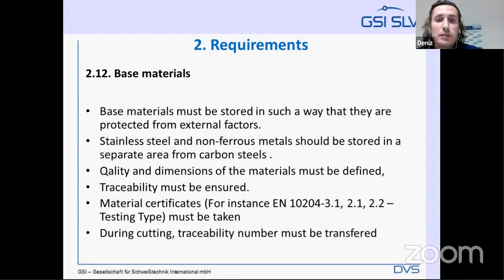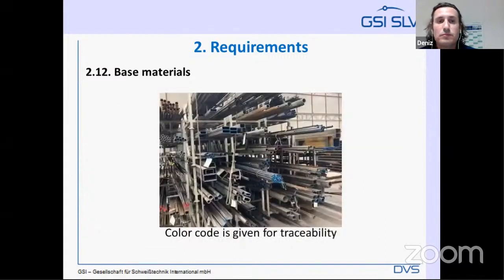Base materials. Base materials must be stored in such a way that they are protected from external factors, for example, humidity, dirt, rust, etc. Stainless steels and non-ferrous metals should be stored in a separate area from carbon steels to prevent corrosion risk. Quality and dimensions of materials must be defined. Traceability must be ensured. Material certificates, for instance, EN 10204 3.1 or 3.2, 2.2, must be taken during the cutting process. The traceability number must also be transferred for base material. An example of color code at the storage area.